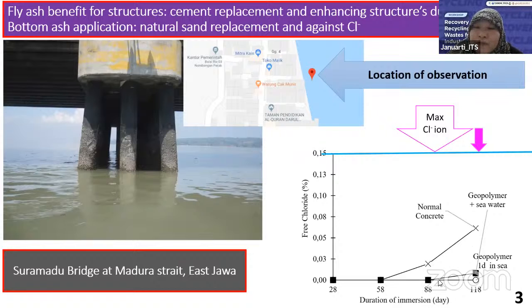And what happened if we use geopolymer and we put it in the seawater? It's very interesting here. We mix geopolymer not with water to make the alkali, but we use seawater to simulate how severe the conditions are if we don't have any tap water or clean water. We just use the seawater to mix the concrete. And this is the way we made our first specimen. We can see here it can entrap or immobilize the chloride ion inside the matrix of the geopolymer.